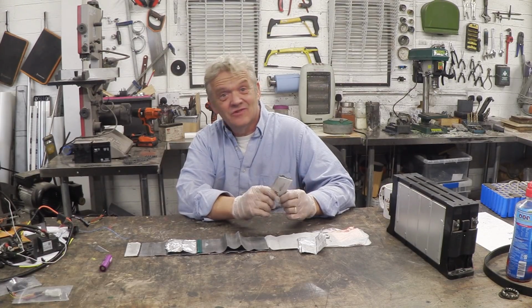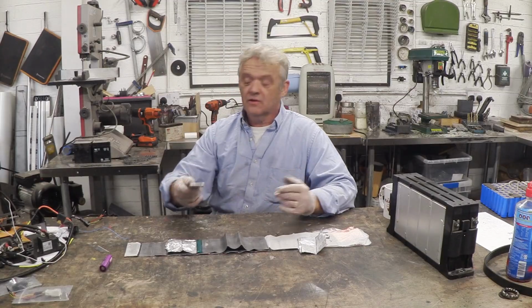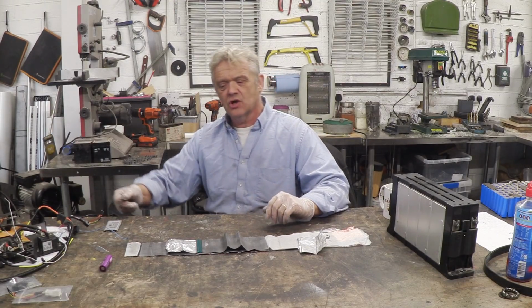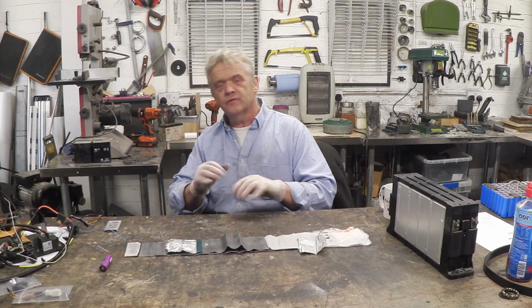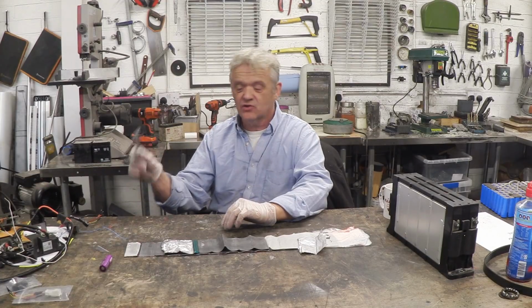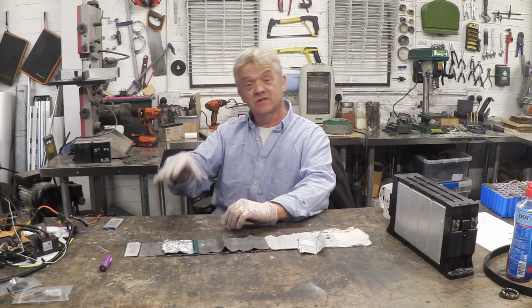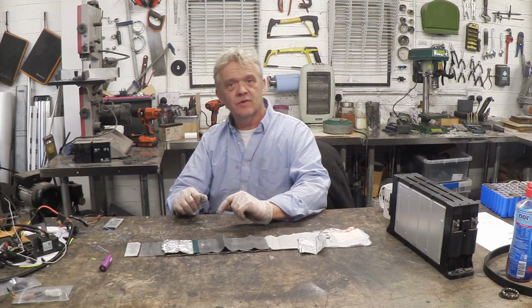The other way to do it is to search up the battery manufacturer and get their technical data sheets, and they'll tell you what that charge voltage is and what that nominal voltage is. So there can be a difference in those voltages depending on the material here. Like I say, this is an NMC battery, and so you find it at a slightly higher charge voltage and nominal voltage, whereas lithium iron phosphate is at a slightly lower charge voltage and nominal voltage, and lots of other flavours of lithium tend to be around about that 3.7 volts. But you can just look it up, to be honest, and it's often a better thing to do.